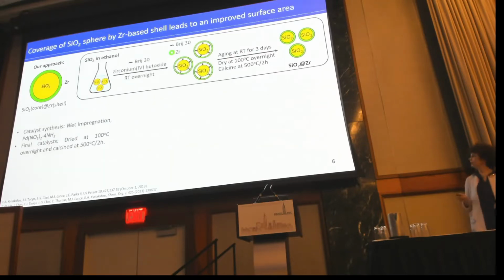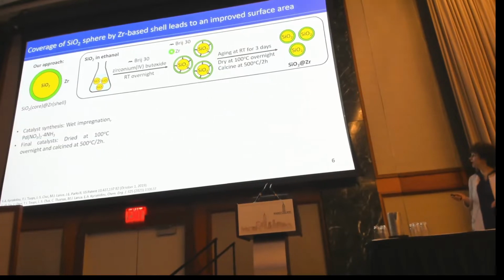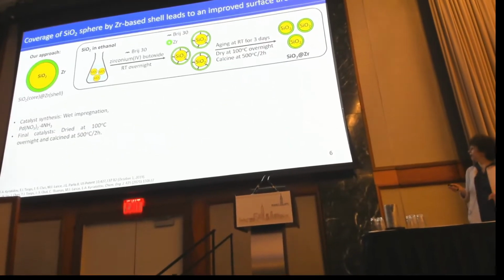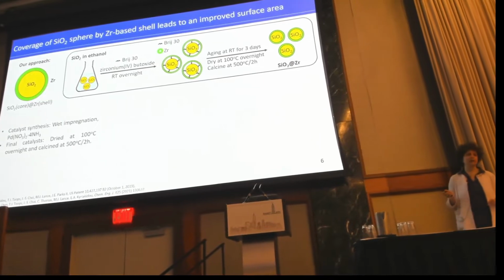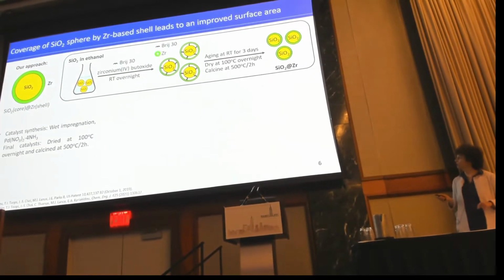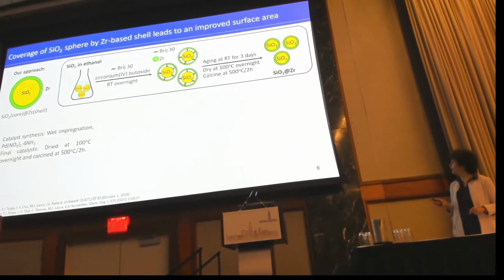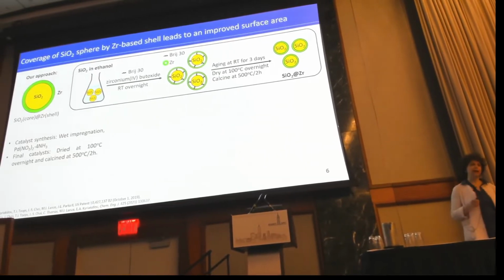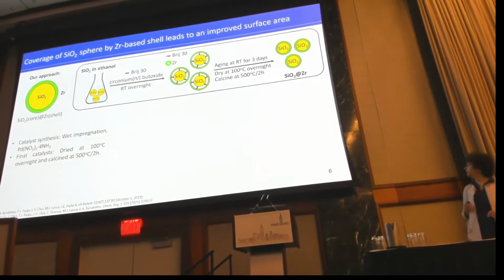background about the synthesis. Initially the silica spheres are dispersed in ethanol, and we add Brij 30, which is a surfactant, and the zirconium butoxide. We allow the solution to age for 3 days at room temperature. Then we separated the solids, dried them at 100 degrees C overnight, and calcined them at 500 degrees C for 2 hours, and then we got the structures you can see here, where silica is the core and zirconia is deposited as the shell.